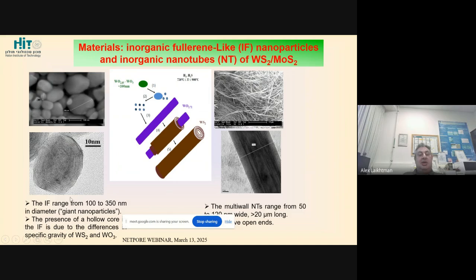But anyway, they are nearly circular particles. They range from 100 to 350 nanometers, so some call them giant nanoparticles. They have a multi-layer structure, a lot of pores, and a lot of defects on the surface, for good and for bad. They also have a hollow core in their structure, and this is due to the difference between the specific gravity of WS2 and WO3, which is the precursor for their synthesis.